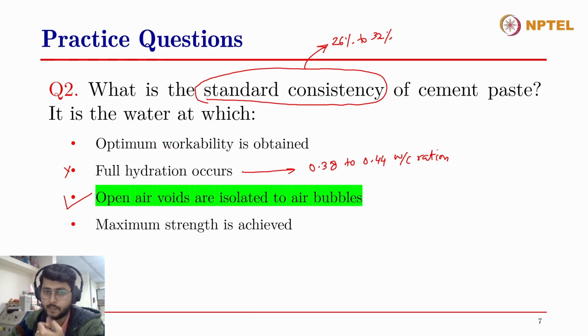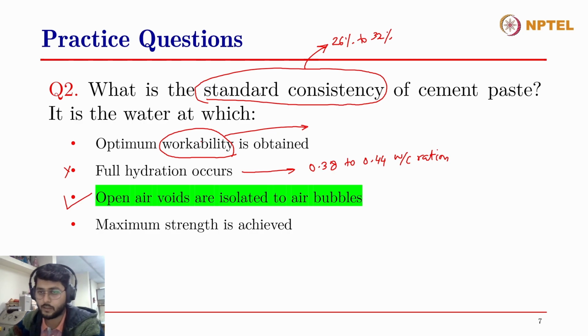Optimum workability is obtained. Again, workability is a very subjective term. Workability is subjective to the kind of application that you're looking to make the concrete for. For example, if it is a slab that you're going to cast, then you would want the workability to be such that the slump would be that of a flowable concrete, let's say around 150 to 180 slump, and you'll be able to pump the concrete because there will be a congestion of the steel reinforcement on the slab or the raft. So you want your concrete to flow on its own and occupy all the spaces so that you'll have a perfect shape of the concrete element, as well as your voids will also be reduced. There will not be any kind of honeycombing in the concrete element.